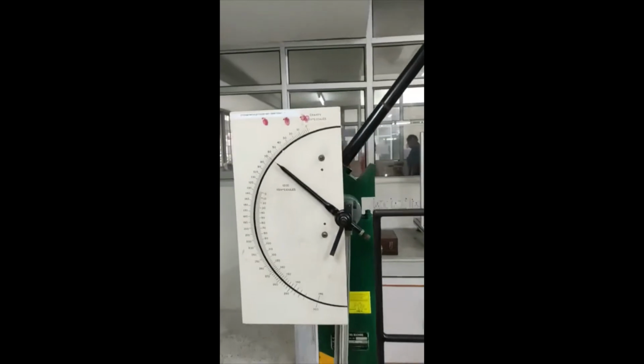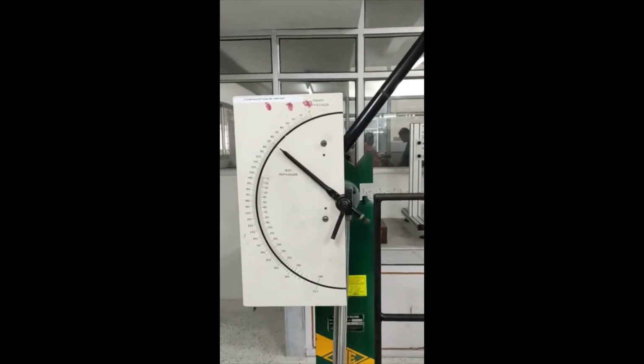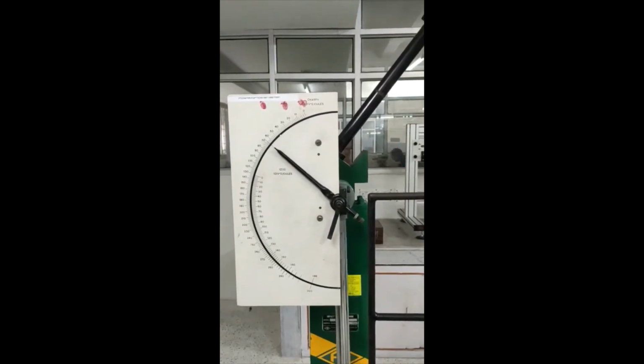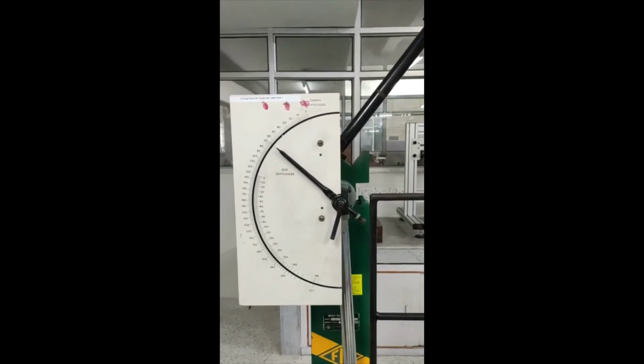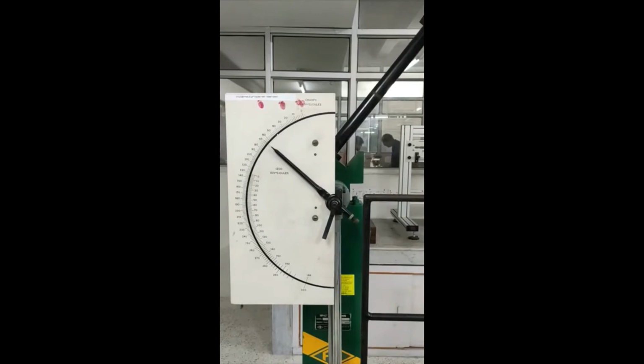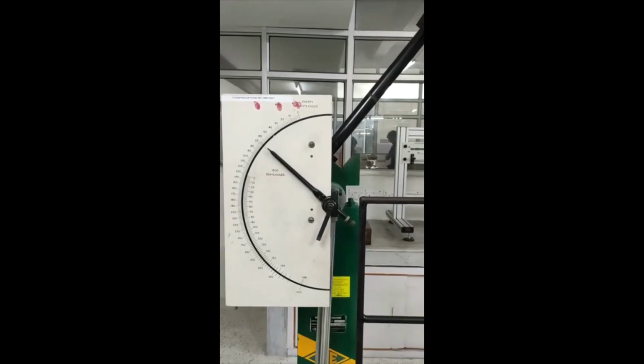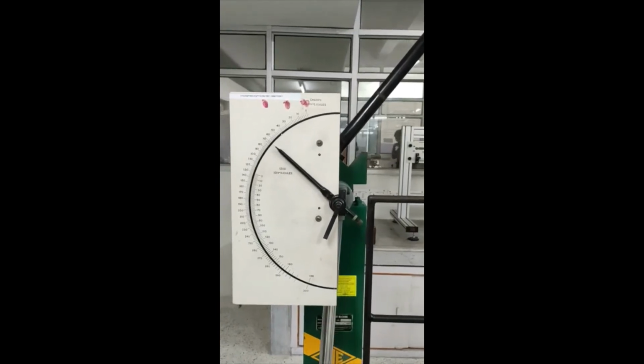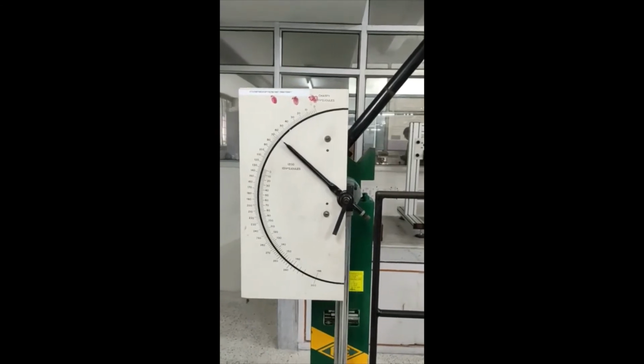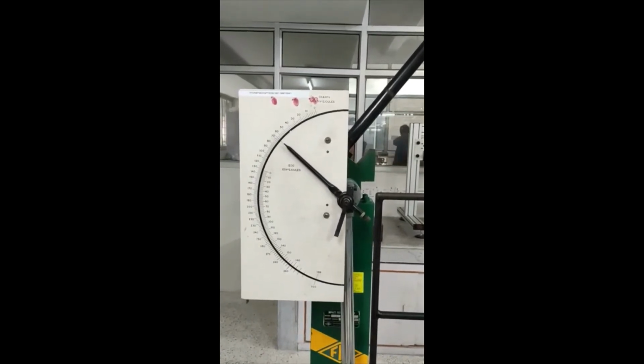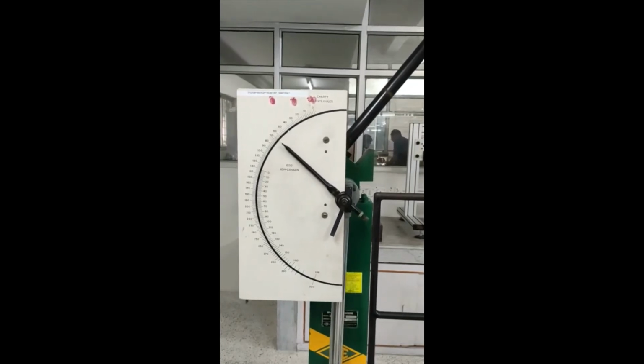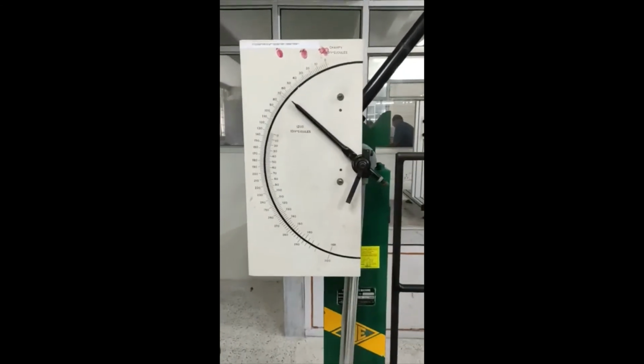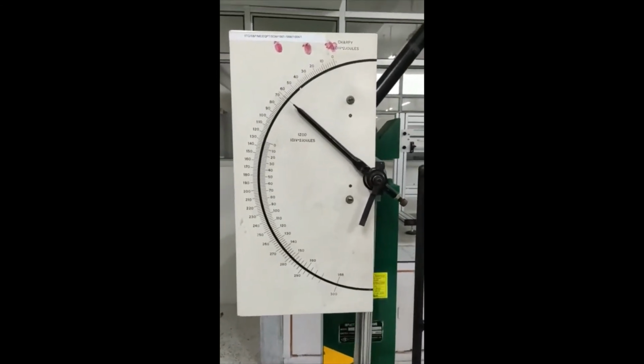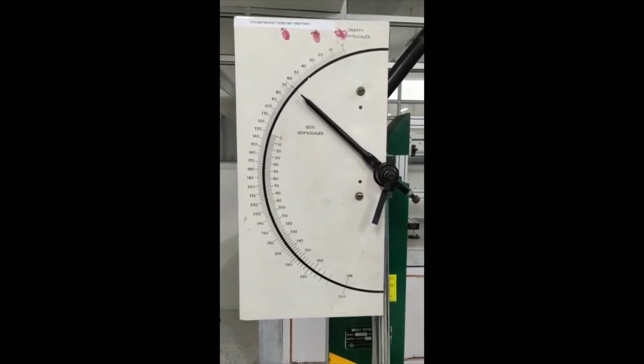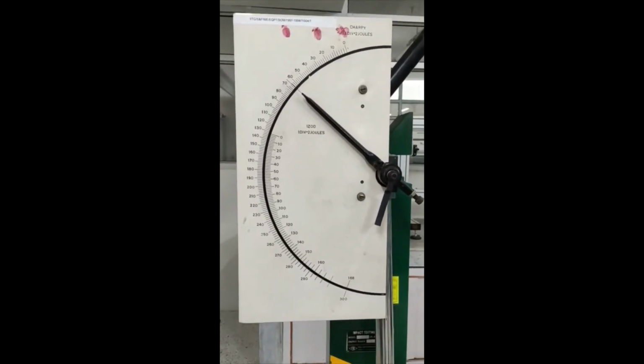So this way we need to perform the Charpy impact test, under different conditions like temperature, weather and other cold conditions, cold material. If we keep it at low temperature, below zero degrees Celsius, then what will happen to the toughness? Will the material change or not? These things we will get. At high temperature, it may take less load. At low temperature, it may take more load. So at different conditions we can perform the test. This test we performed at normal room temperature, because in this machine, the specific environment room temperature chamber is not available, so we have to perform it at normal room temperature only.